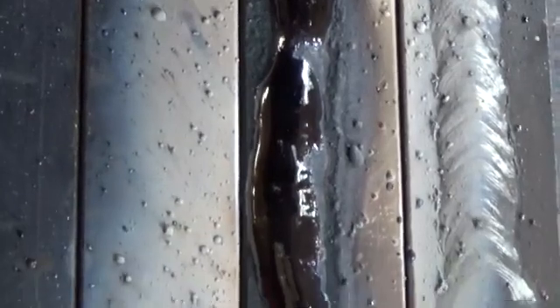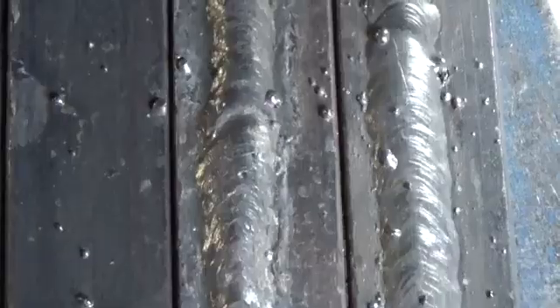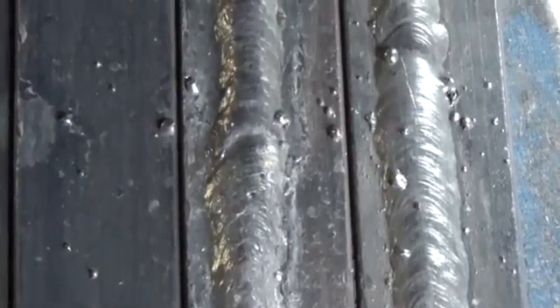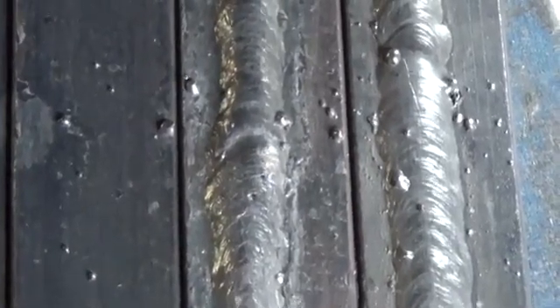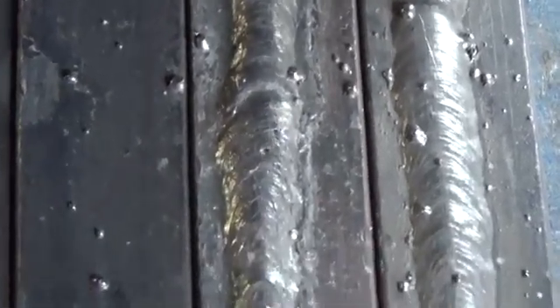The puddle is practically difficult to control. The liquid metal instantly spreads in all directions. Because of this, electrode manipulation is complicated. It is difficult to get the identical width and height over the entire length of the weld. Look at the slag covering. It has gaps and discontinuities. All this leads to defects. Let's look at the weld carefully.